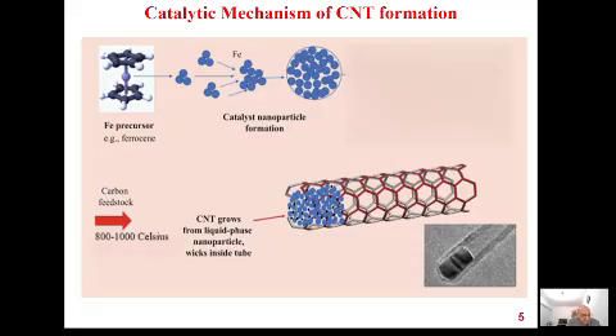Thus, the final ferrum containing multi-walled carbon nanotube structure is formed. The iron nanoparticles encapsulated within carbon nanotubes are thought to enhance the electron donating properties of the nanotube walls, which is favorable for electron transfer during the oxidation process.